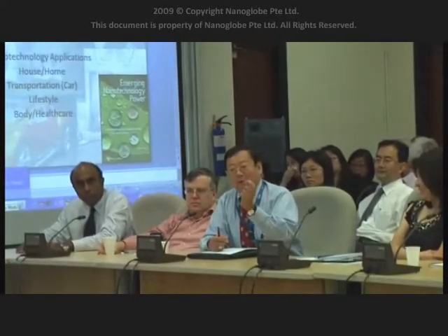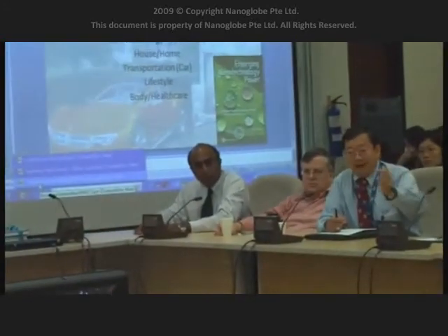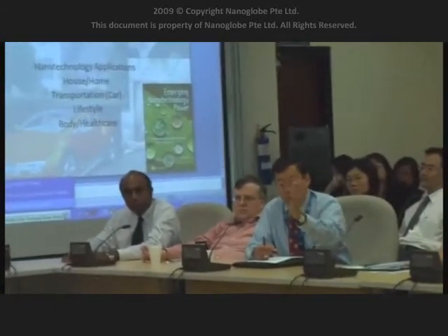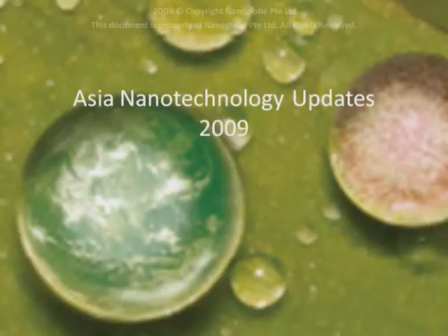We called it submicron channel. But these are very equivalent to the gramicidin channels that allow the passage of cations through the polymer membrane. So that's why Nafion is used in fuel cells, but actually more extensively in the chlor-alkali industry, where you have cationic transport.